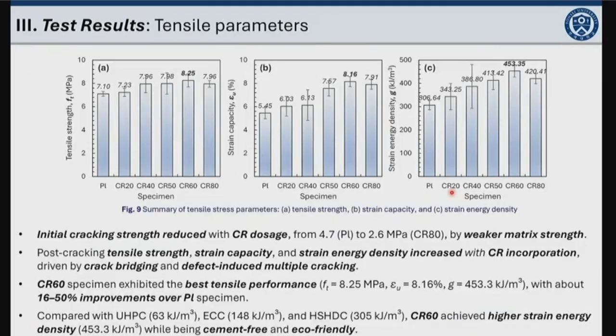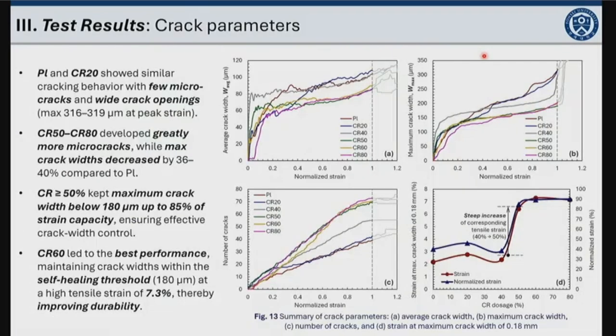This is the summarized tensile parameters. As you can see, the crumb rubber dosage of 60% was the optimum, providing the best tensile performance with a strain energy density of about 453 kilojoules per cubic meter, which is approximately 1.5 times higher than that of the plain sample. And this is the crack parameter analysis.